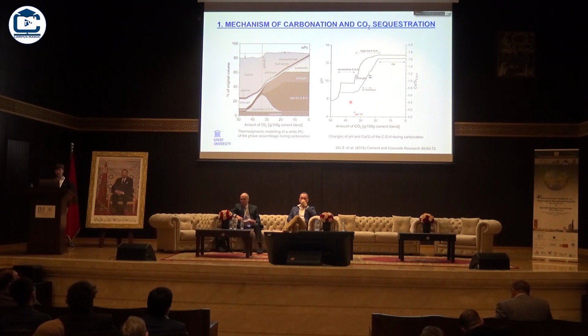So to start with the mechanism of carbonation, thermodynamic modeling is a very good tool to get some insight on what's really happening. And this is just the overview of what is changing if carbon dioxide is bound in, in this case, a white Portland cement paste. So we have to go from the right to the left of this picture, and then you can see in this cement paste there is quite some Portlandite available. And if carbonation is starting, this Portlandite is transformed into calcite.